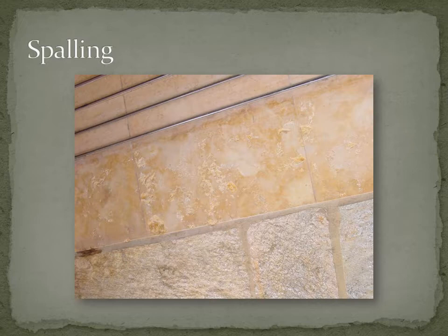If you fill that with epoxy and grind it, it'll be a harder fill. It won't scrape out as easily, but that piece of epoxy that you put in there, it will flake out probably within a year, because that epoxy's not letting it breathe, and that's the problem that happened in the first place, or why it happened in the first place. So that's why you like to use a cementitious filler or grout. And there's actually a few grout colors that right out of the box look very similar to this stone. So this flaking process is called spalling.